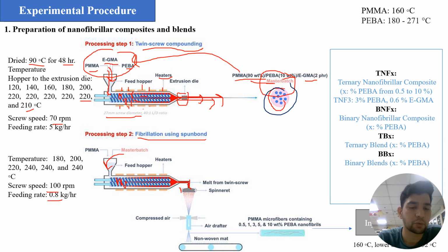Okay, here is a question: why did the author use master batch? Master batch we usually use to dilute the small component, like PEBA, which is in the minimum concentration. We need to dilute it, but we need to disperse it well. So for that, first we disperse it in the PMMA, and then when we make the master batch, we again mix with PMMA, so it disperses well. So that's why we use master batch. Maybe someone has another idea; the idea which I got is this.